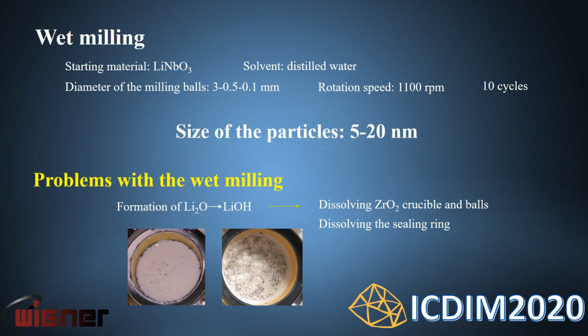The first thing we saw was the black parts of the sealing ring in the crucible, you can see in the picture. It's not only because of the mechanical wearing, but because of the formation of lithium hydroxide, which is a strong base and dissolved the sealing ring, the zirconium dioxide crucible, and the balls as well. So it must be eliminated because of the pollution of the sample and because of the damage of the crucible and the balls.